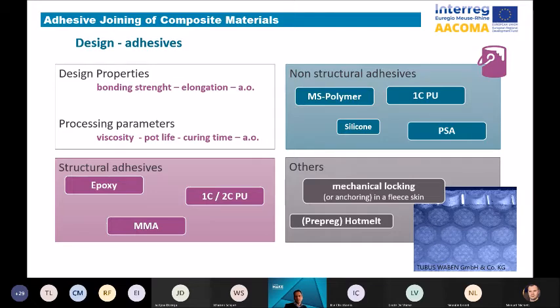For structural bonding, epoxy is the most used adhesive. It has high strength on various materials, is good temperature resistant and has good properties against aging. But when you can't guarantee an even and very thin bond line, epoxy loses quite some strength, and methacrylate or MMA adhesive may be the better choice. For non-structural adhesives, sealant types such as an MS polymer or one component polyurethane can be chosen with their excellent sealing and damping properties. Maybe you can also think about a PSA, a pressure sensitive adhesive, or just a tape. A very quick adhesion on smooth surfaces. This can be very interesting.